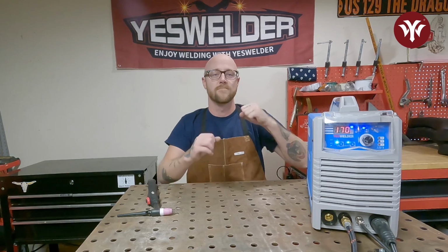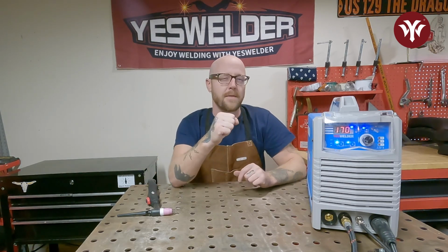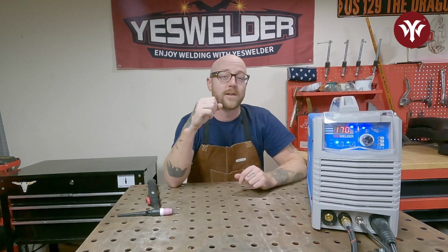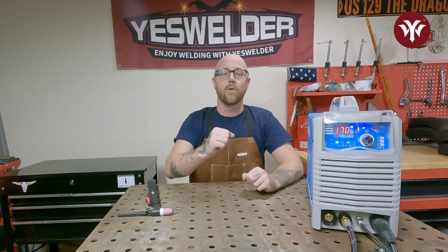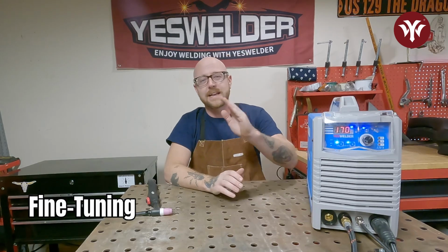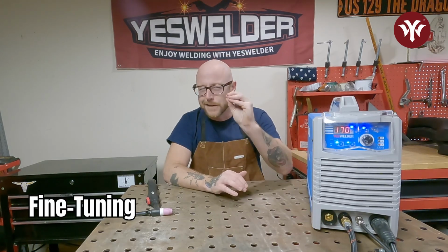Again, very little control. You're melting the base metal, which is good, but the problem is you're melting the filler rod and everything's kind of going everywhere and it's not being focused on that joint that you want welded. You're also introducing too much heat. The metal's heating up too much and it's causing a poor weld. So let's turn it down a little bit and let's try to find just that perfect spot.